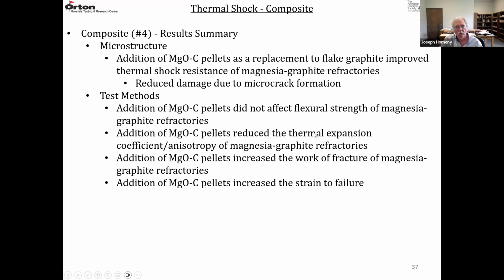The addition of the pellets reduced the thermal expansion anisotropy, which helps control the damage, reduce the damage during thermal shock. The addition of the pellets also increased the work of fracture, and they increased the strain to failure. So by reducing the anisotropy, improving the work of fracture, improving the strain to failure, and maintaining a reasonable strength, they actually made a somewhat better MgO carbon refractory with a lower graphite content. So in terms of thermal shock, they actually improved the refractory.